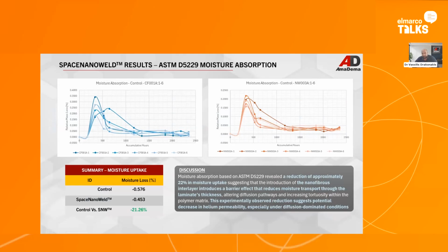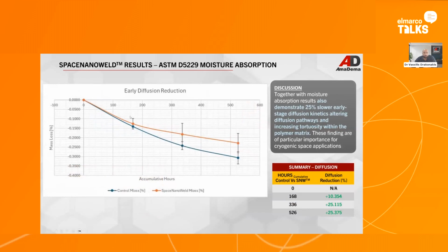Another very good result here is the improvement in moisture uptake. So we have a 20% better moisture uptake compared to the control with the presence of the nanofibers. And this actually makes this prepreg material suitable for launcher structures that carry liquid fuels. And you can see here, compared to the control and the NanoWeld system, how differently the diffusion is reduced. So basically the nanofiber-enhanced composite absorbs less moisture.